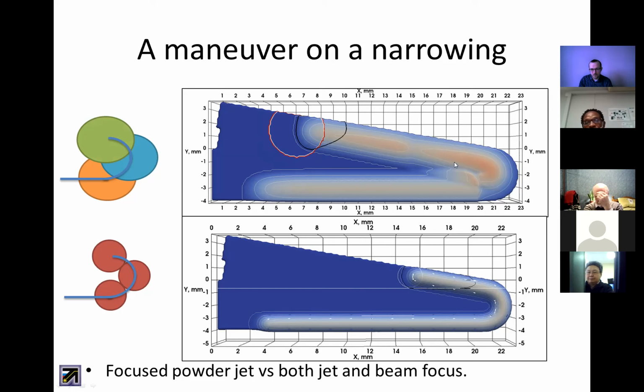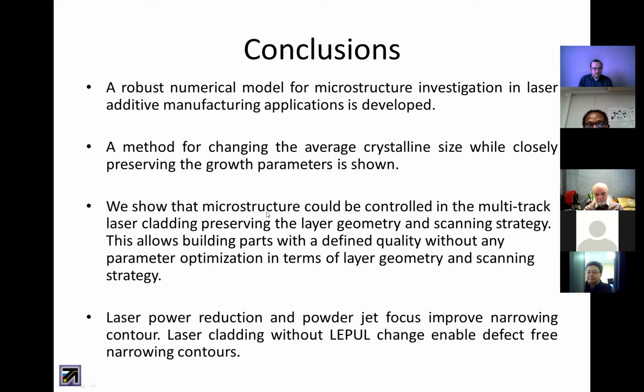But still we've got these defects which can be harmful. And we show that only the focused powder jet and the focused laser beam, without an increase in energy density per unit length, can make such defectless narrowings. So here are my conclusions.